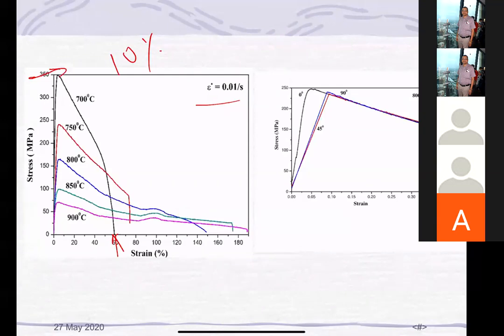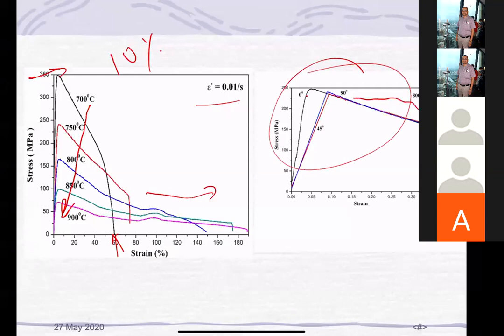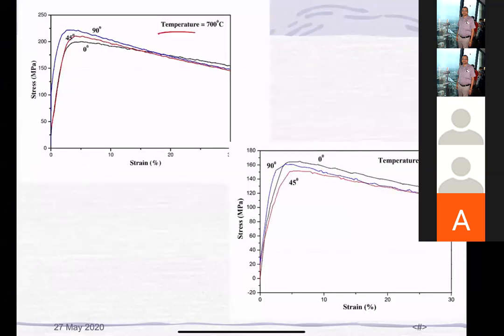And one phenomenon you can see from here: when there is an increase in temperature, see how the curve is flowing. Percentage elongation is increasing, yield strength and all these parameters are going down. It's natural for every material. And from here, at 0, 45 and 90 degrees to the rolling direction, there is a lot of variation. Of course, in this region there is not much variation. But this indicates the material is quite anisotropic. Same thing at 700 degrees centigrade: if you superimpose 0, 45, 90, there is a variation. At 800 degrees centigrade, there is a variation.